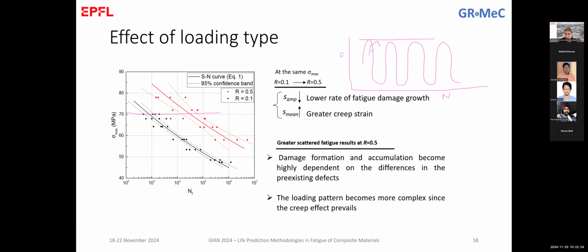Could be something like this, which means for the same maximum stress, we have an average. So we have a continuous, if you like, stress on the specimen, which is higher than this. And this difference that we see can be attributed to the creep effects that prevail in this loading case compared to the loading case of R equal to 0.1.